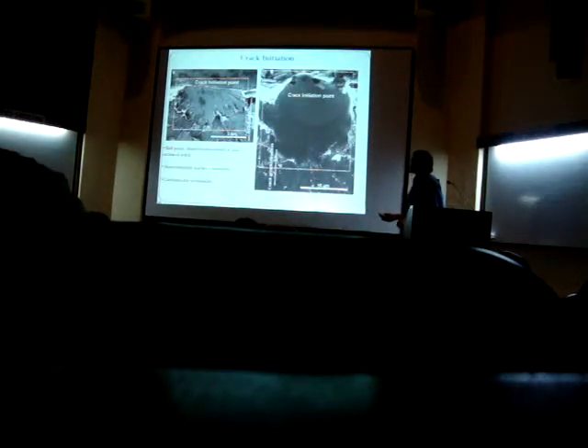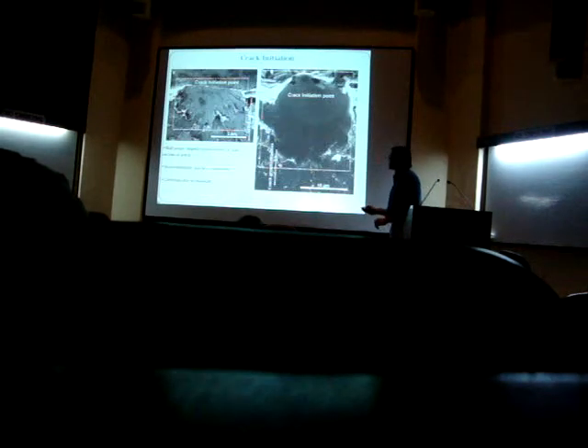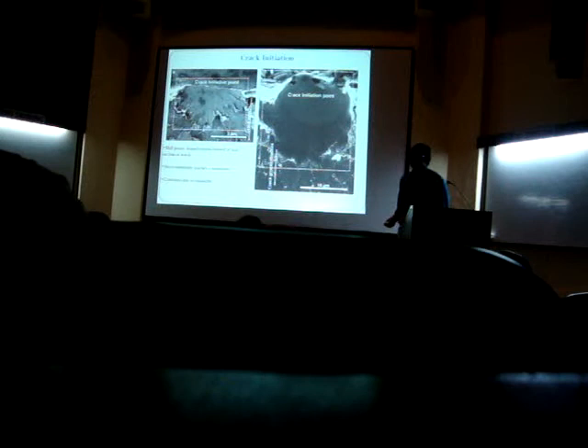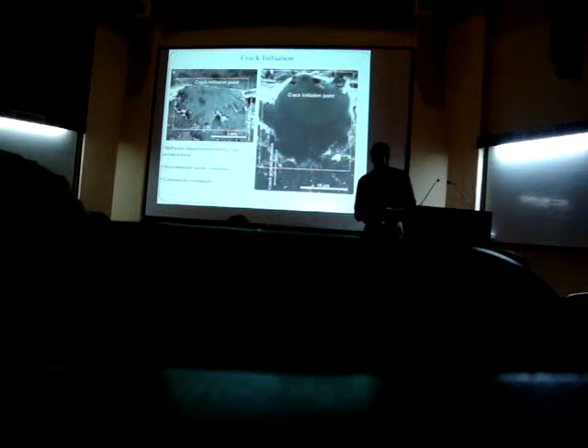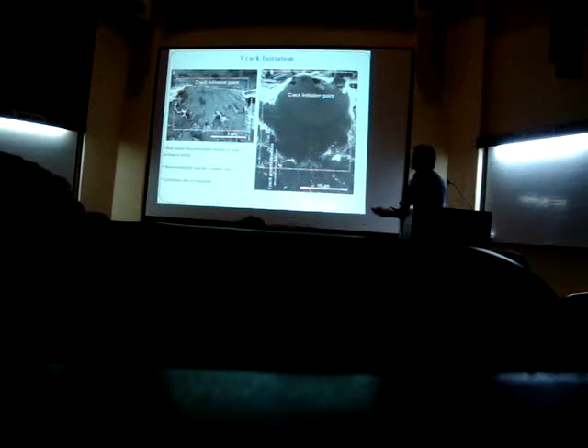Now we will study aspects of fracture, which are crack initiation, crack growth, and the micro mechanisms, using these features. First we go to crack initiation. At the center of the notch front, this is your notch edge, you see a circular feature like this. This particular feature is only found in metallic glasses, and it is pretty featureless. This indicates that if there is a particular featureless area, you should have something undergoing cavitation, right? I mean, it expands to a level and then it pops.